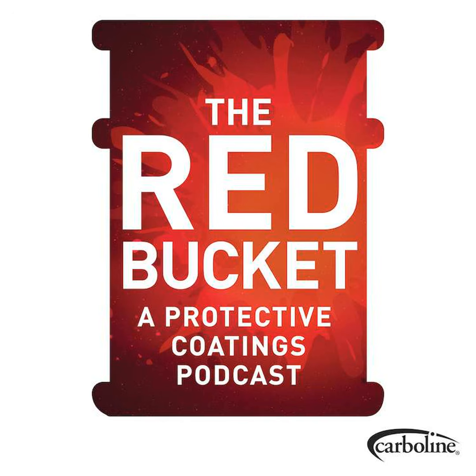Even with traditional insulation, there are insulation materials designed for cold and materials designed for hot. Insulative coatings are more of a cool to hot application. Above 350 degrees, there are some that have a little bit higher temperature threshold than that. What happens if you apply a traditional insulative coating that's good to 350 at 500 degrees is the inner layer is going to char. The outside might look good, but the inner layer is going to char. It's not going to be bonded to the surface, and you have a mechanism that can start corrosion again because you're not bonded to the surface. Those are the two main ones that I veer away from.